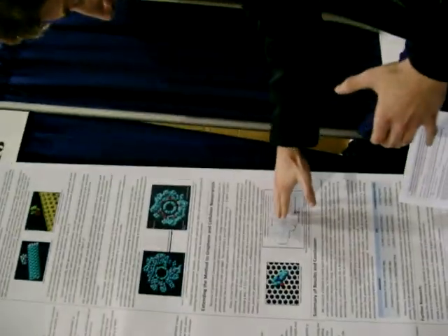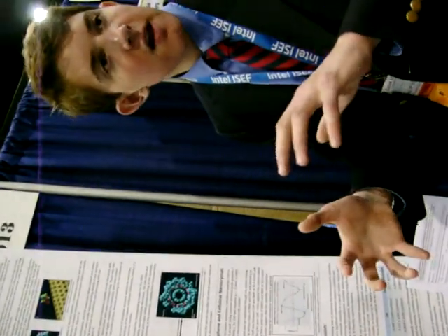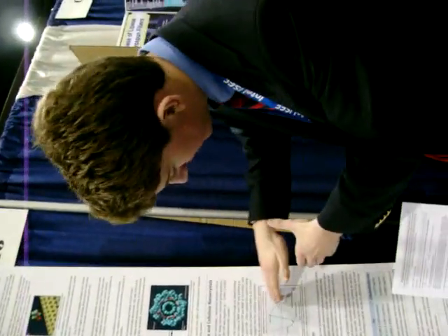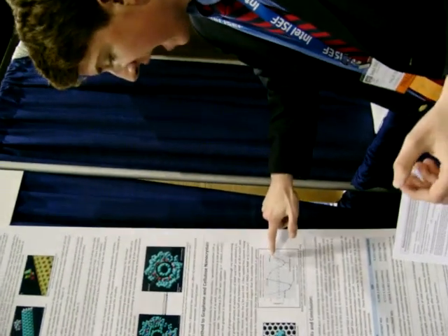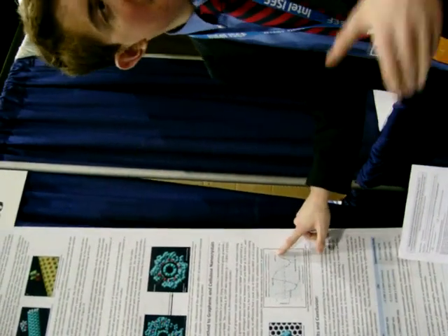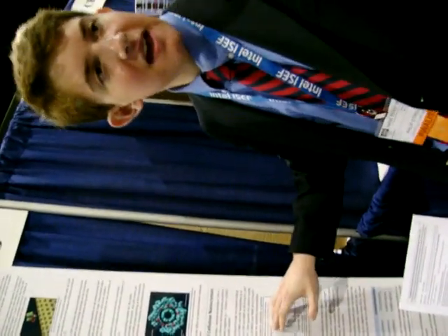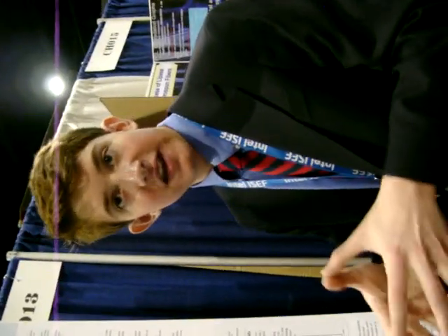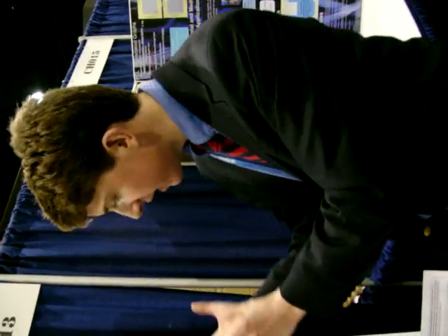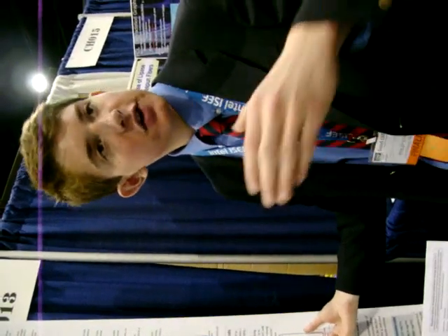And so then, applying my method to the cellulose nanocrystals, I was able to very efficiently, in just about 2 weeks, zoom in on a peak for the nanocrystals by mixing NMP and DMSO. And what's interesting is that the pure NMP and the pure DMSO solvents on their own could not dissolve the nanocrystals. It was only when I used my method and mixed the two solvents together that chi became negative.